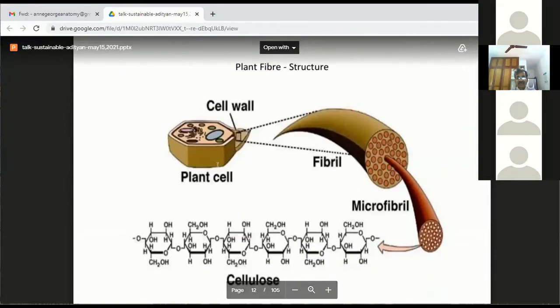This is something very interesting. If you look at the hierarchical structure of plant fibers, look at the plant cell. This is quite big. Macro. And you can have a fiber. Look at this. This is again a macroscopic structure. But inside this fiber, you have lots of microfibers embedded. You can separate them, so you get microfibers. And inside the microfiber, you see lots of nanostructures. You see? So you can work in three different landscapes, three different hierarchical landscapes.